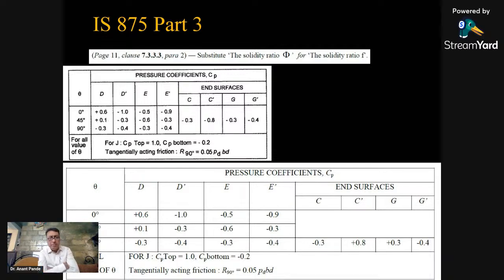Now, pressure coefficient Cp: in the earlier code, if you look at this particular table for the end surfaces, for C dash, it was minus 0.8. That was a typographical mistake, and they have come out with C dash now plus 0.8. See how much difference this can make. Probably you were thinking that there will be suction. Now it is not suction. It is the pressure on the sheds.